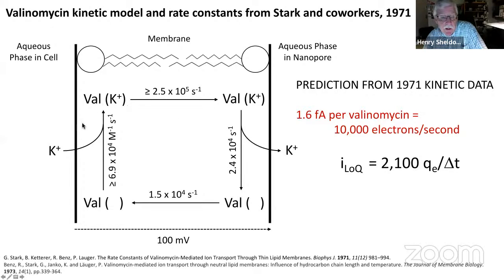The first step over here is the valinomycin picks up the potassium. There's a rate constant for that. It's transported across the interface. There's a rate constant for that. It's released and then transported back. And the slow step is valinomycin without the potassium diffusing back to the left side. If you take the rate data published 50 years ago, you can compute that the current per valinomycin should be about 1.6 femtoamps. That corresponds to 10,000 electrons per second.